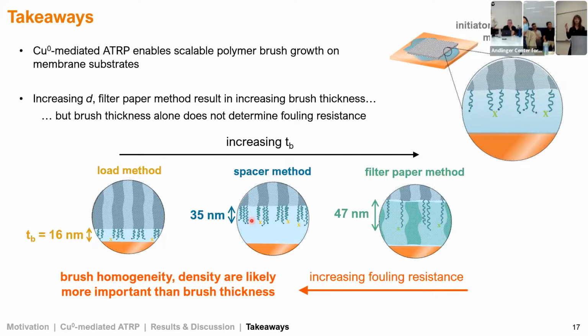There's probably some optimal point, which people have looked at with respect to thickness, where if you grow too long, you're decreasing the permeability of your membrane. And that reduces performance separate from fouling. I think there could be something interesting here to look at how density affects permeability. Maybe a denser but thinner layer will allow us to achieve higher permeability, but also the same or better fouling resistance. But yeah, I think that's a very interesting point. Hopefully that answered.